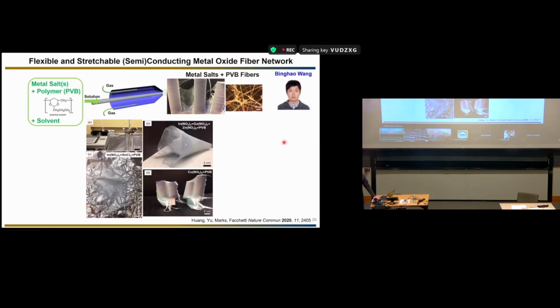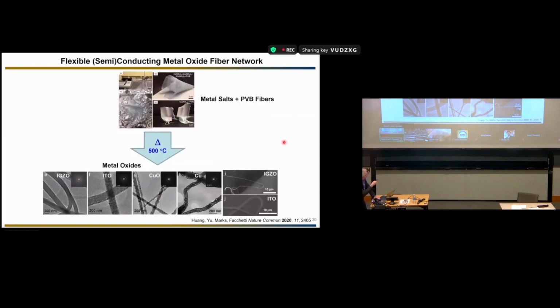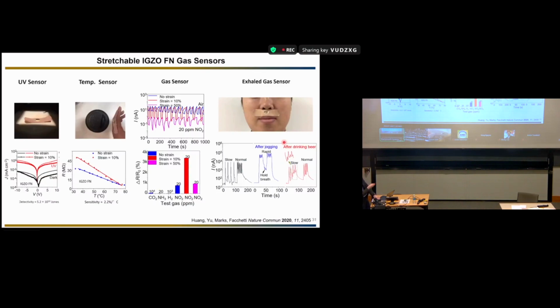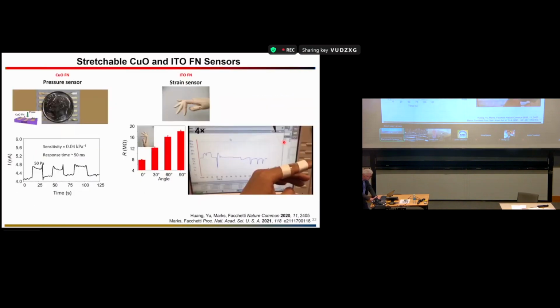This fiber is not the oxide. These fibers are the polymer, which absorb the precursor of the oxide. How do I go from this to the oxide? By burning off everything. We take this fiber, we burn them off, and then we get oxide fiber, which has the composition of the salt I've been using. Of course, we cannot do it directly on a plastic or elastic substrate. We typically do the conversion of the fiber precursor into the fiber oxide on a silicon substrate, and then we transfer them to an elastomer, and then we can make TFTs, we can make a resistor, and we made a number of sensors and things like that. That's an example of a strain sensor, pressure sensor. We did a few.